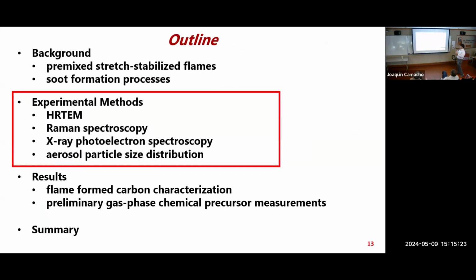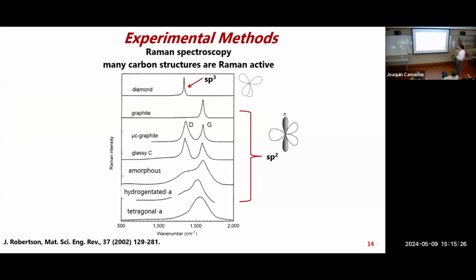So experimentally, we'll look at these characterization methods. For example, Raman spectroscopy is very useful for carbon materials. What Raman spectroscopy does is it shoots a photon at this material. It's a surface weighted measurement, and based on the response of the phonon modes or the material properties, it'll shift the light by the Raman process. And what you're measuring is the shift in wave number, I should say Raman shift here, that indicates a shift in the light as a response to the vibrational modes of this material. And carbon is very sensitive to this.